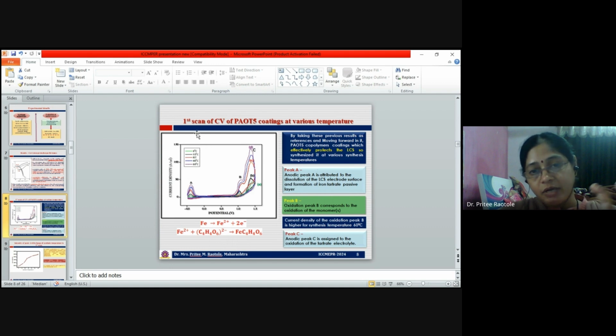The first scan of cyclic voltammogram of these PaOT5 coatings is characterized by three anodic peaks. Anodic peak A is attributed to the dissolution of low carbon steel electrode surface and formation of iron tartrate passive layer. The oxidation peak B corresponds to the oxidation of monomer, and the current density of oxidation peak B is higher when it is synthesized at 60 degrees Celsius. The anodic peak C is assigned to the oxidation of tartrate electrolyte.